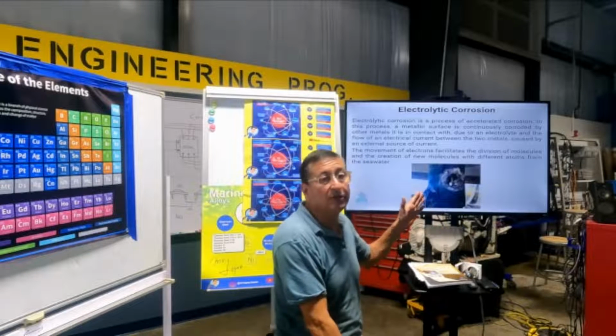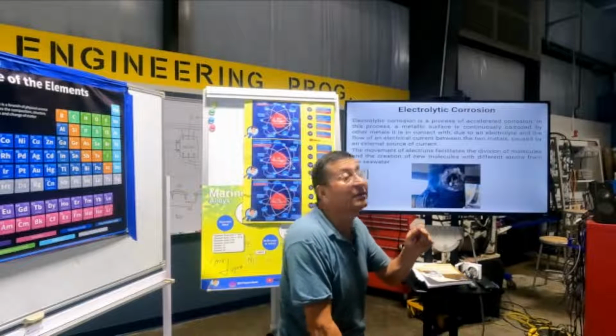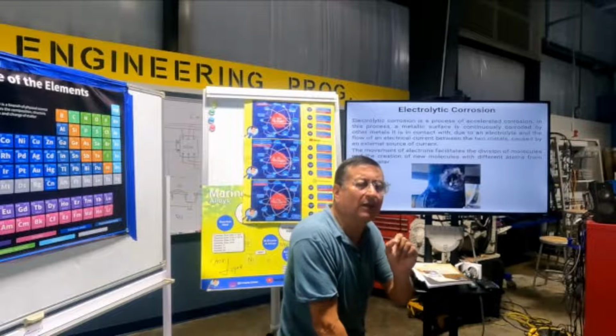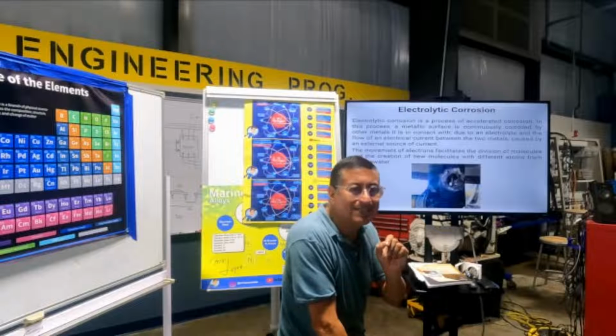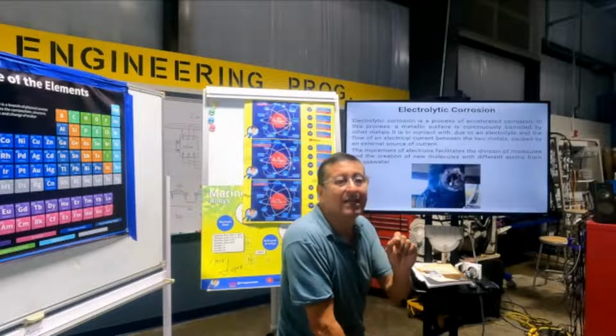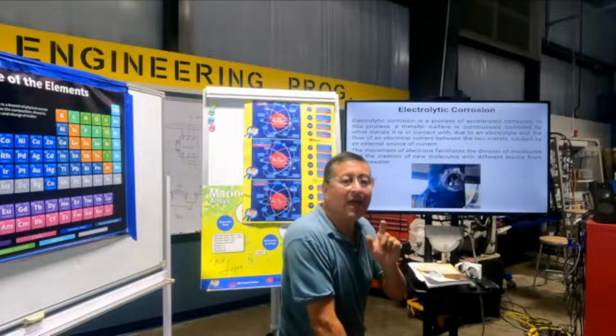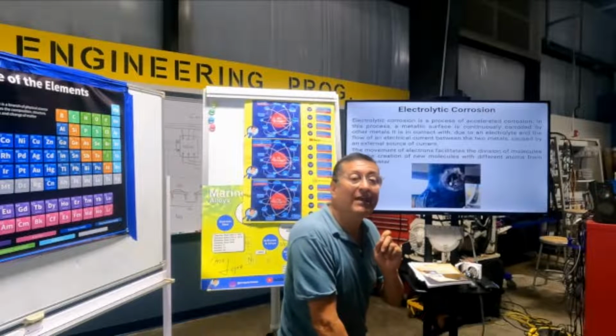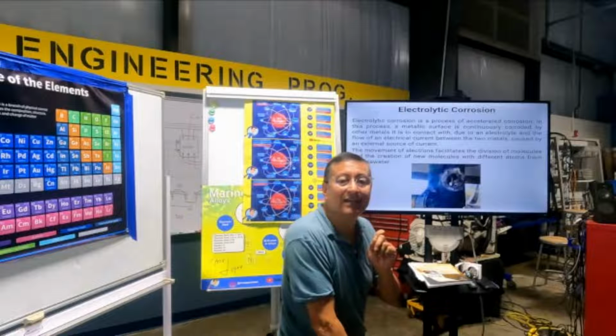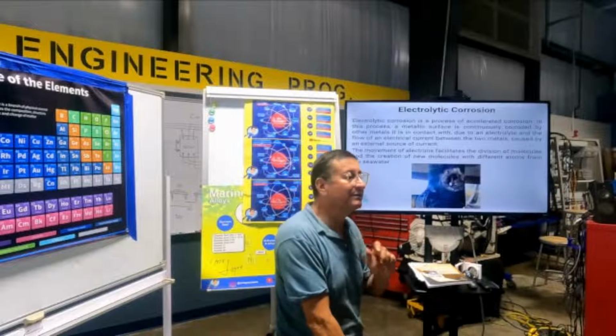The fittings for an aluminum tank should be stainless steel, Series 300. You remember which series in particular is the best? 316, 316L, low level of carbon. The 316L is the same as 18-10, or 18-8. You remember? 18-10.